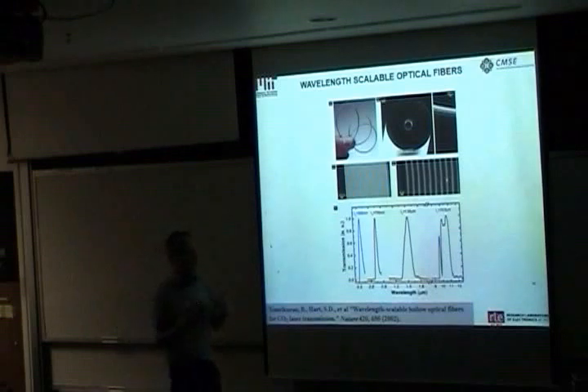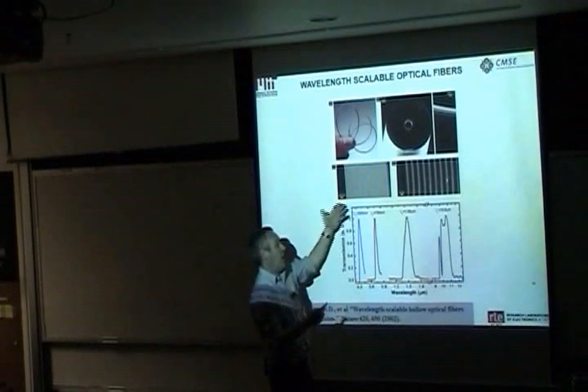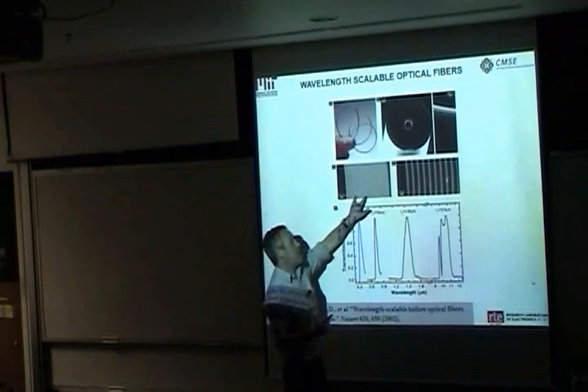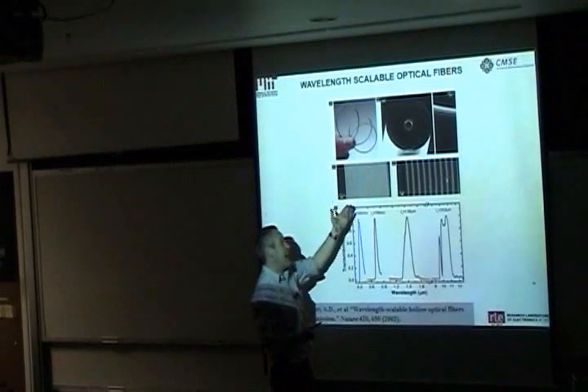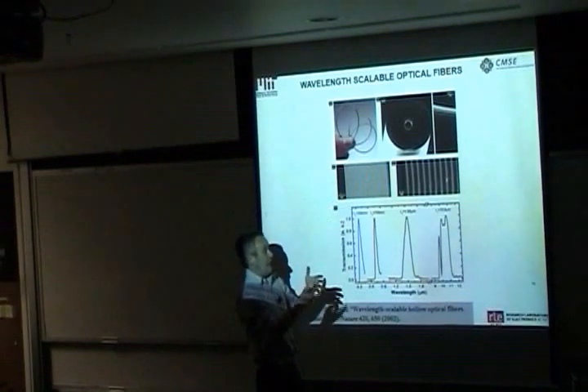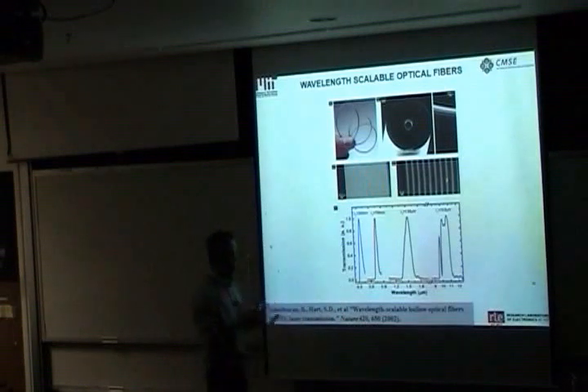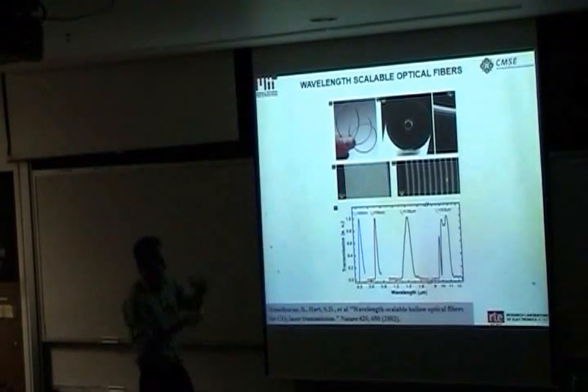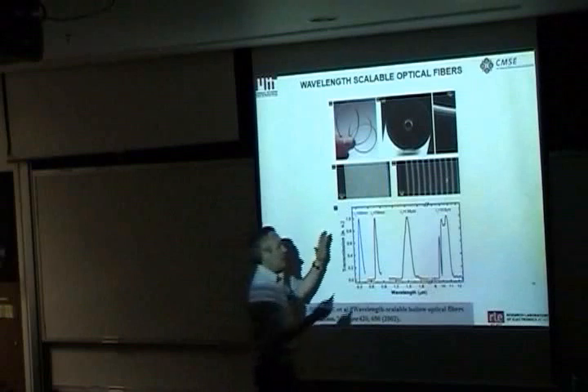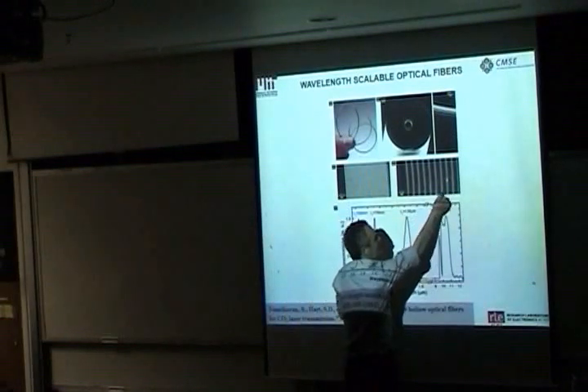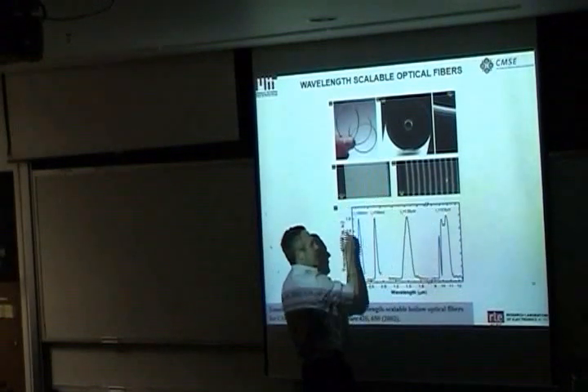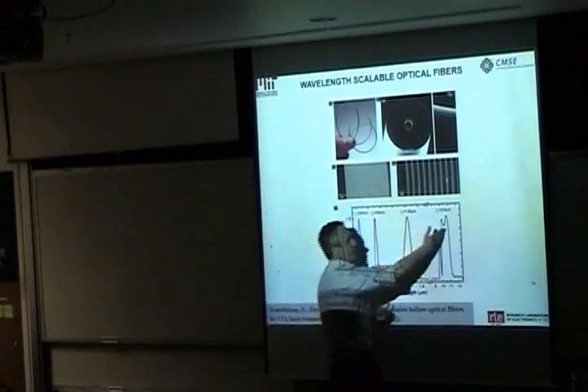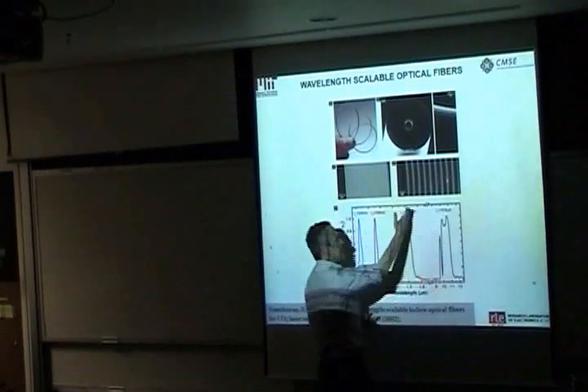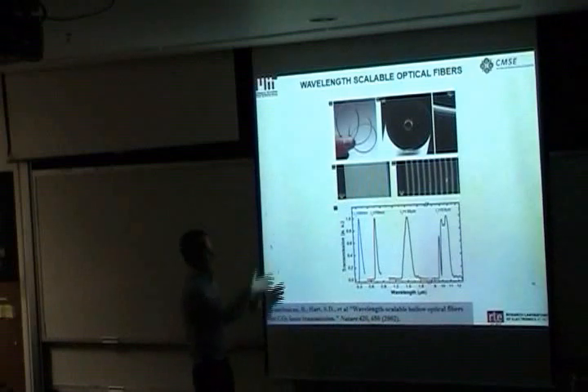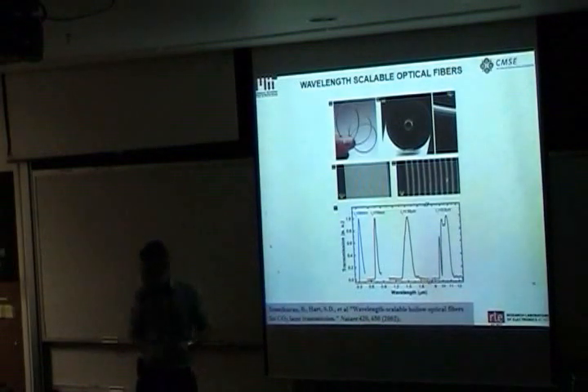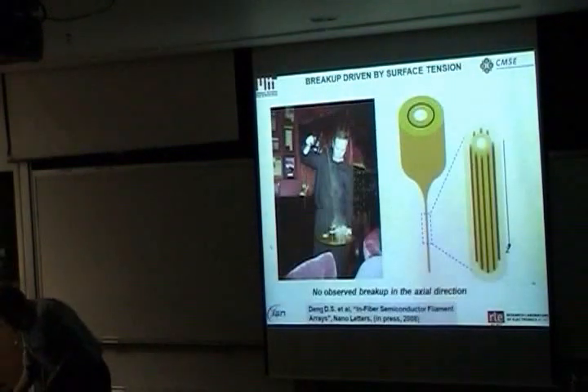So it's not that the materials are transparent or anything, actually they're highly lossy, but it is getting the period right that gets you this very rapid evanescent decay. Obviously we're using materials that have very large index contrast, and that defines a large potential here. And then you could scale the layer thicknesses down as you're drawing these fibers, and your fiber goes from transmitting at 10 microns to 1.5 to 750 nanometers and even to the UV. So this was the first demonstration.